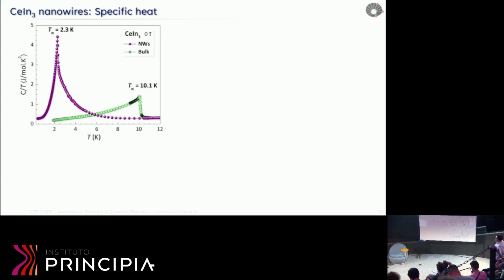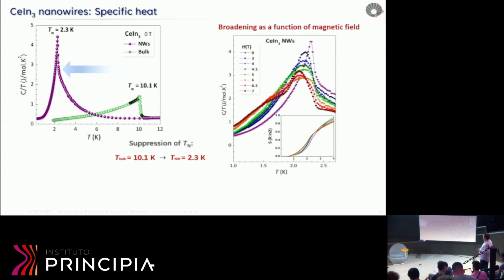So let's look at the specific heat data right now. Again, clear suppression of this transition. The peak is a little bigger. That has to do with the alumina template over there, because we have to measure everything together. But what's important here is the suppression of this temperature. This is a really drastic change.